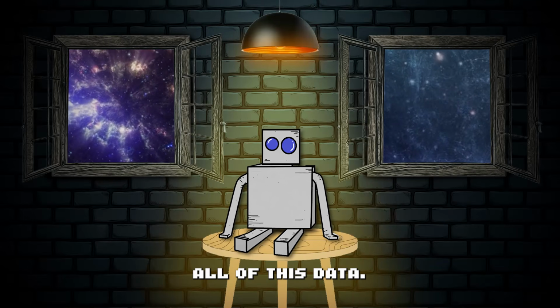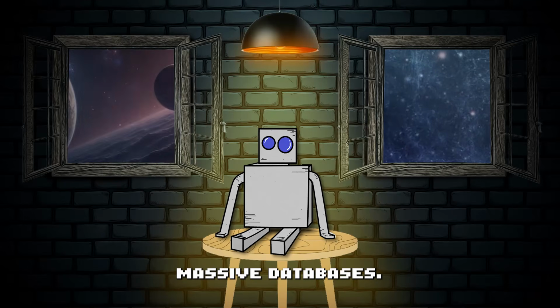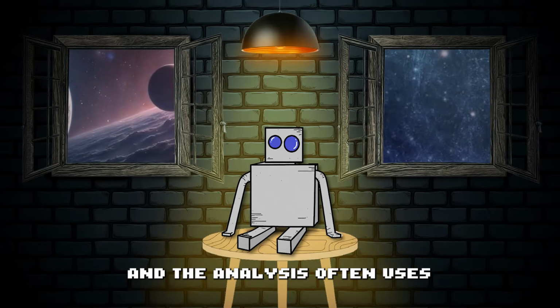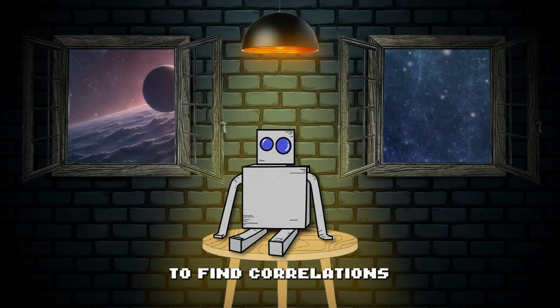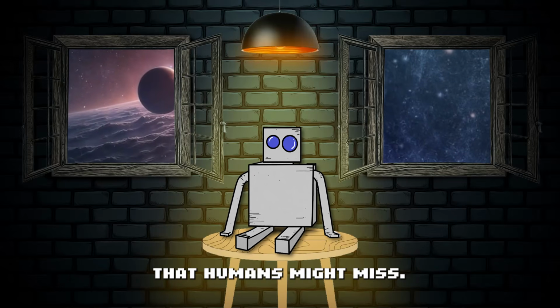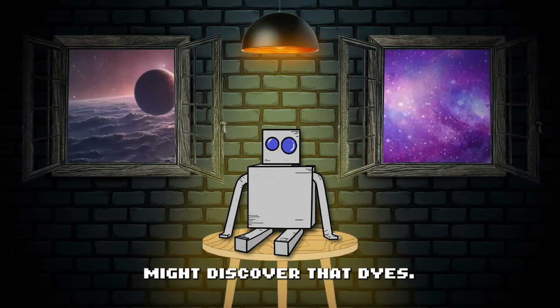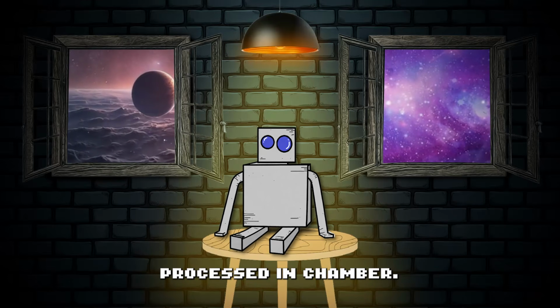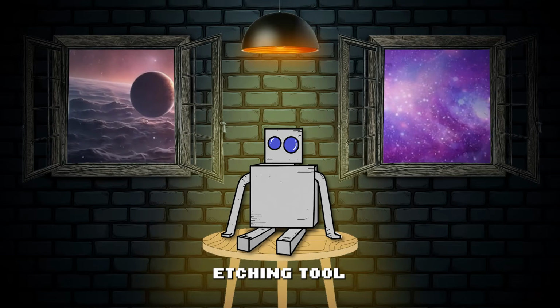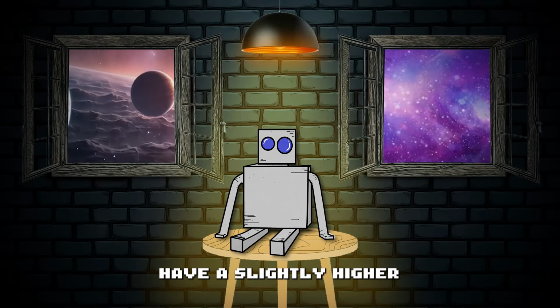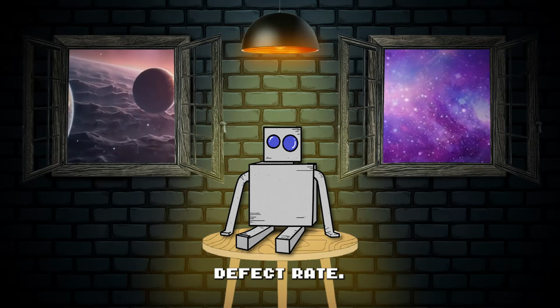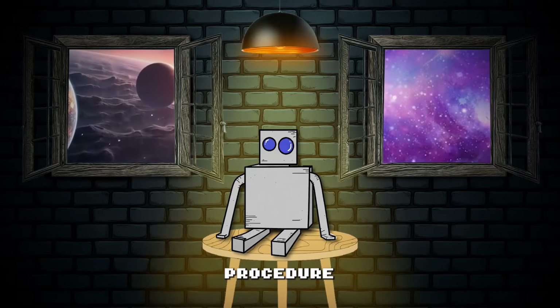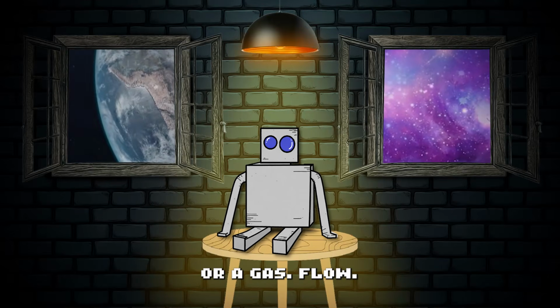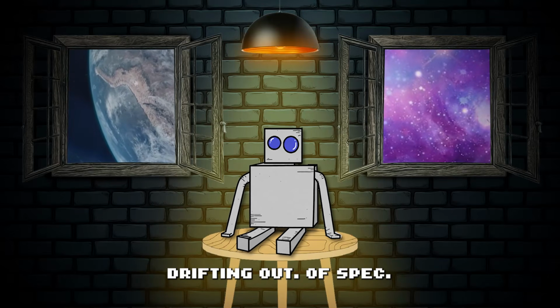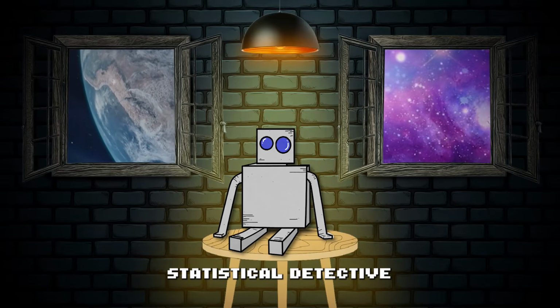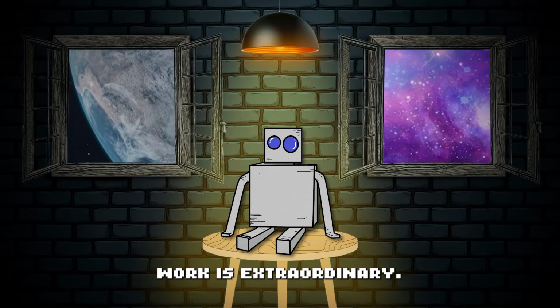All of this data feeds into massive databases, and the analysis often uses machine learning now to find correlations that humans might miss. A yield engineer might discover that dies processed in chamber 3 of a particular etching tool on a Tuesday afternoon have a slightly higher defect rate and trace it back to a maintenance procedure that wasn't quite right or a gas flow controller that was drifting out of spec. The level of statistical detective work is extraordinary.